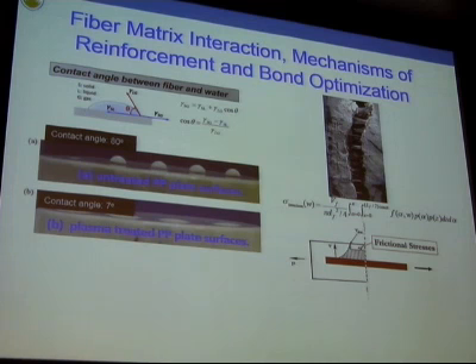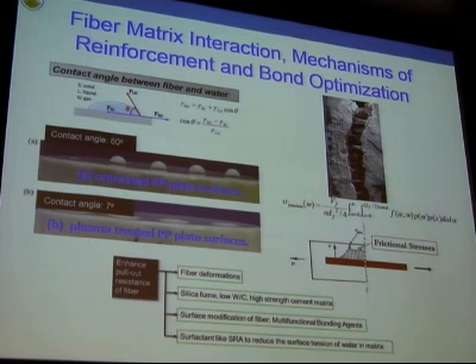So again, over the last 30 years, a number of new techniques have been generated to increase the performance of one single fiber, which is now pulling out at a very high pull-out force without fracturing. And there are other methods: fiber deformations, silica fume use, surface modification, surfactant use, and a number of other studies that have allowed us to generate these fiber reinforced concrete materials, which now have the type of characteristics which I call an elastoplastic response.